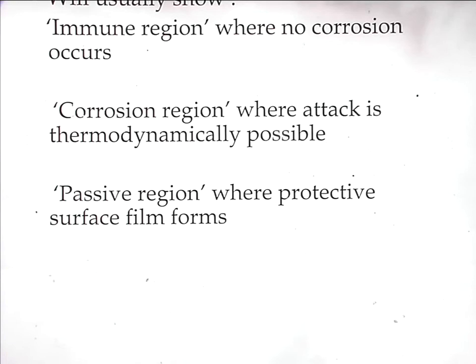At higher potentials, you go more anodic, then you begin to get corrosion, and these shaded regions here, and also at high alkaline pH over here, are the corrosion regions for the steel. And then in this intermediate region here, you've actually grown a film of Fe3O4, which is magnetite, black oxide, and that actually is passivating. So we've got immune, corrosion over here at this end as well, the shaded areas of corrosion, and passivity in this middle region here.